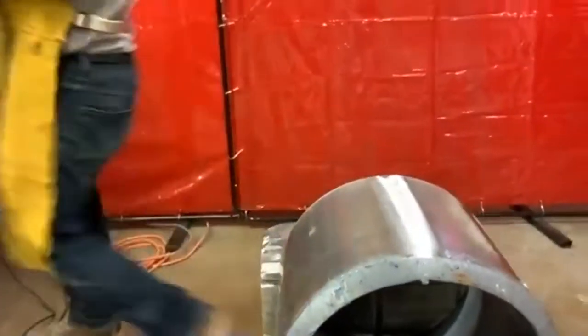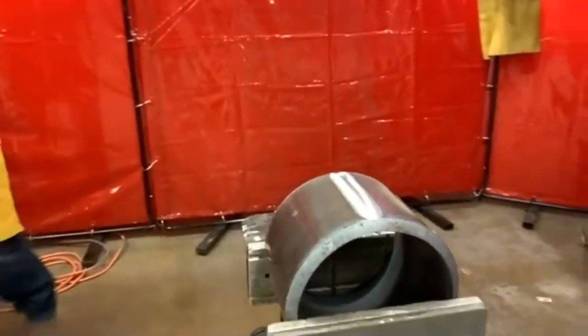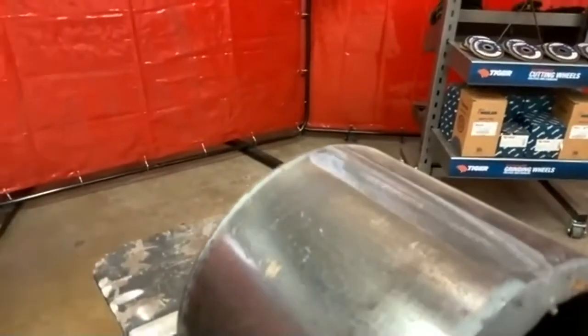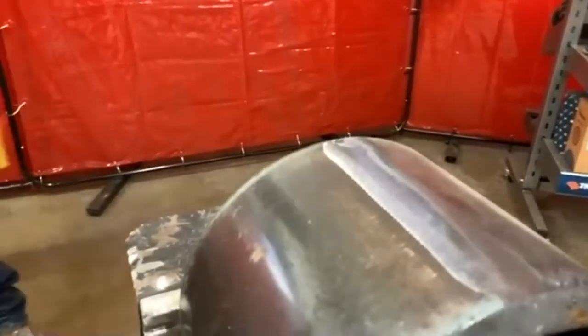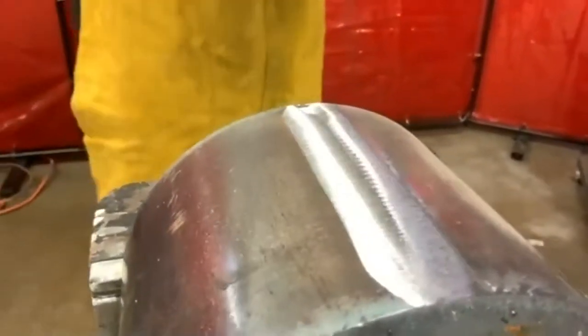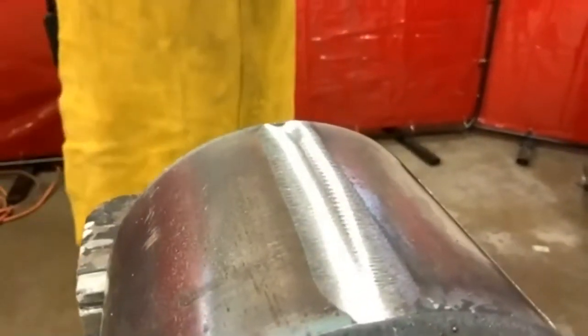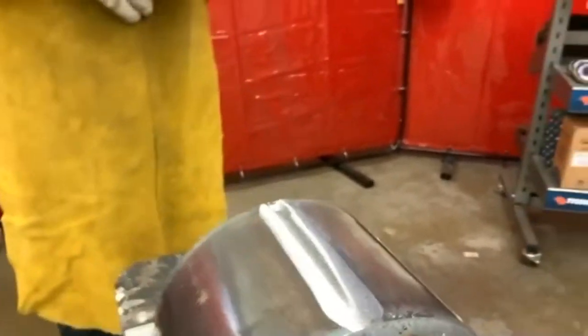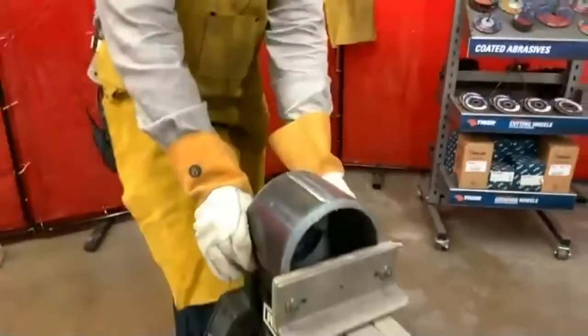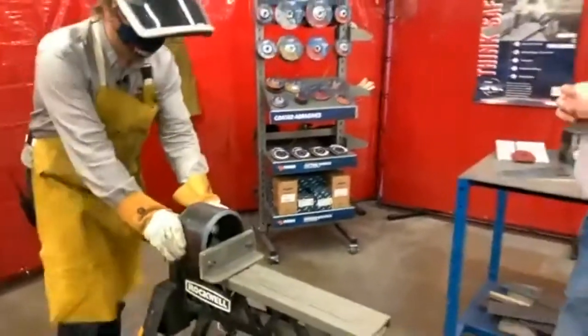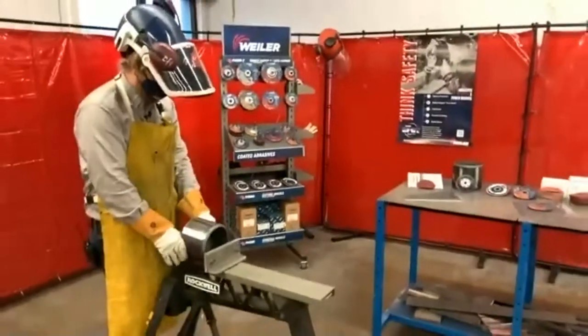Very consistent in maintaining that curve and that arc, right? And again, the biggest thing that I noticed from back here, the easy part of the job, was that it never flinched when the abrasive came in contact with that mill scale. Never lost any of that cut rate, never had any of that sliding. The disc just kept going, and you're able to do the same or more work in less time.